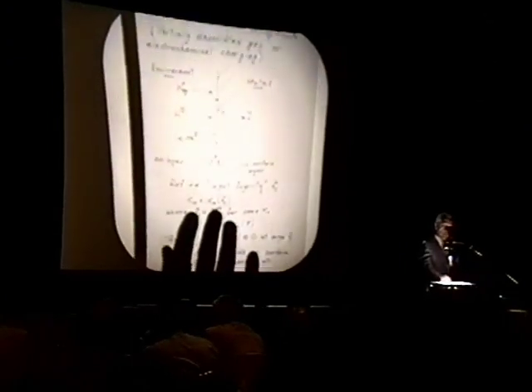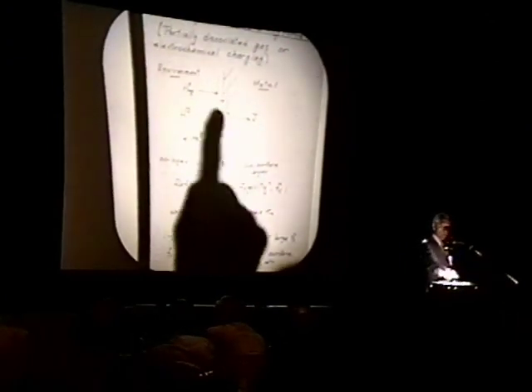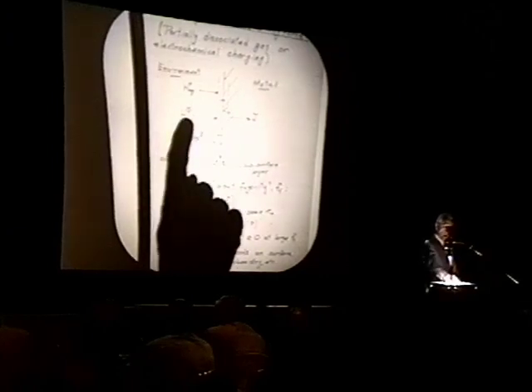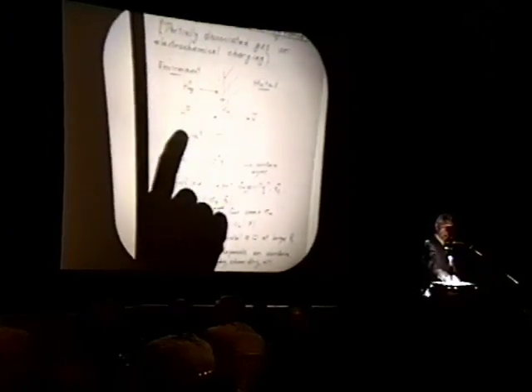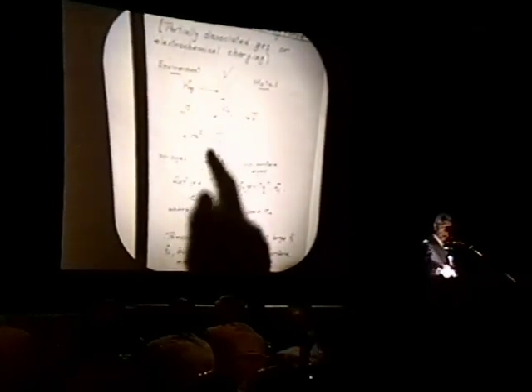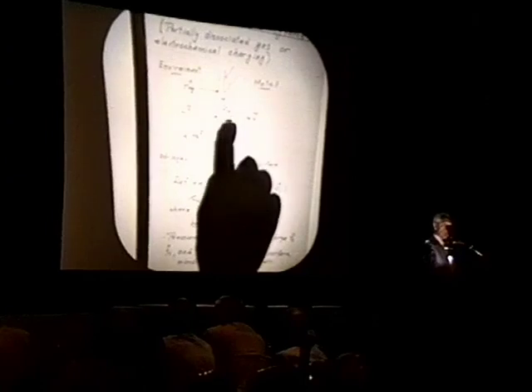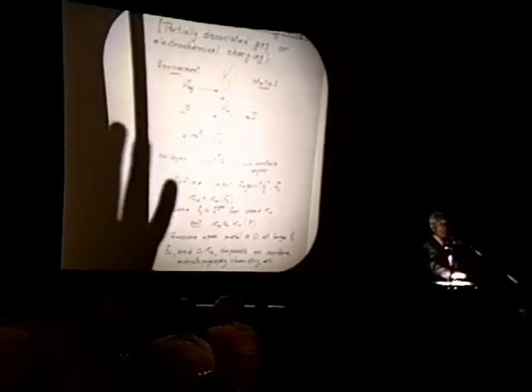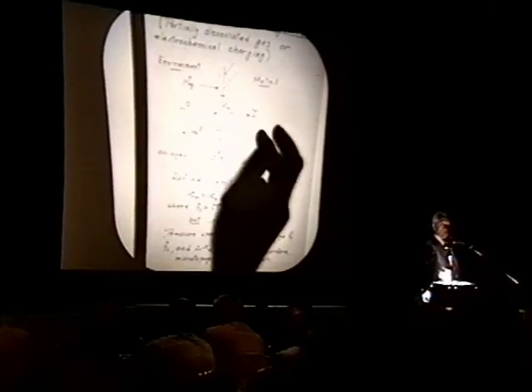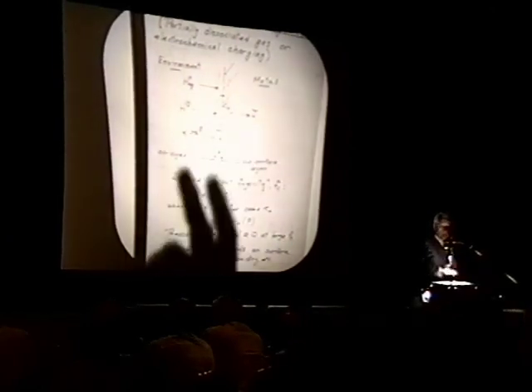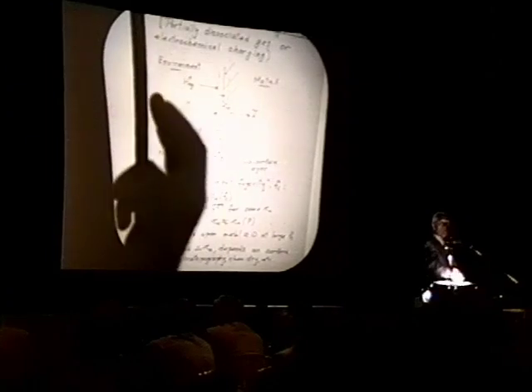Let's go on now to charging from other than molecular gas. Consider here two cases and one figure. The case of charging from a partially dissociated gas, say when you have a hot tungsten wire in a low pressure gas phase, you generate hydrogen atoms, hydrogen ions. They are bombarding the surface, and they form some kind of adsorbed layer, and then that generates a C0 inside here. You cannot describe the driving force between this phase and the solid phase in any thermodynamic terms, because in the case of the partially dissociated gas, we don't have thermal equilibrium out here.